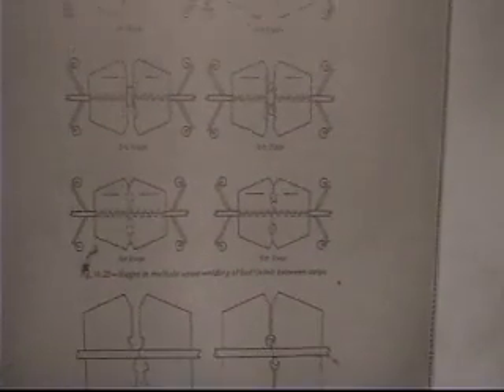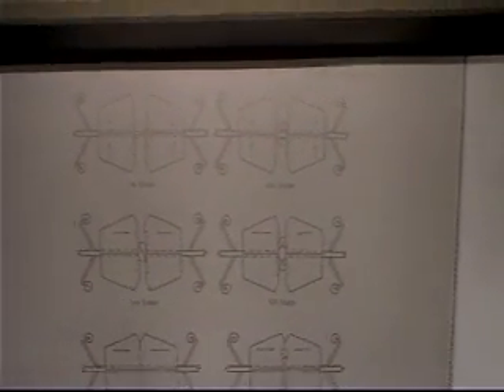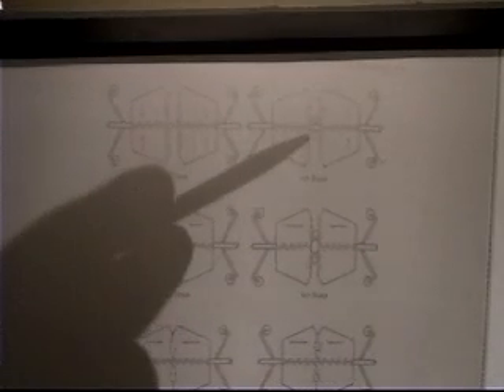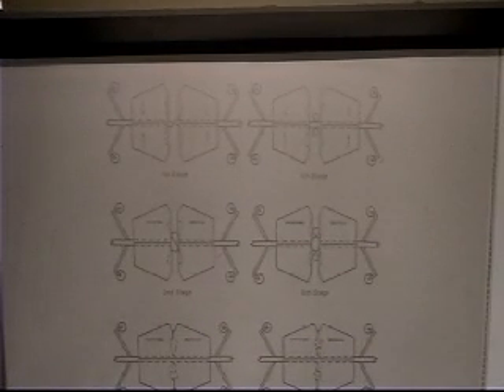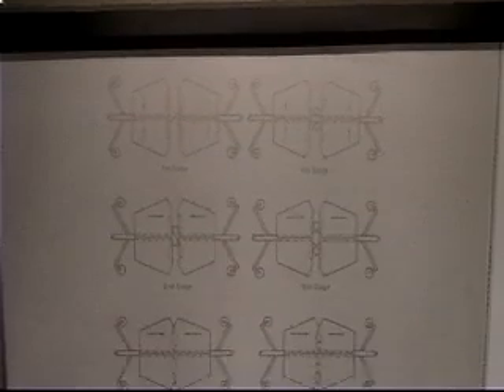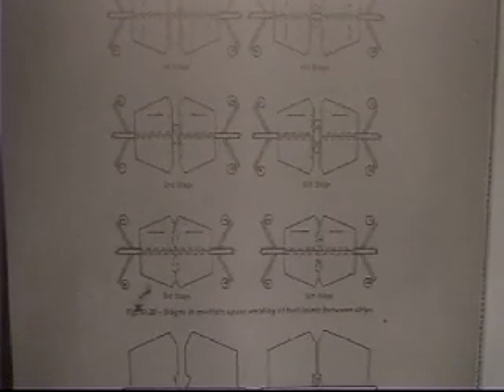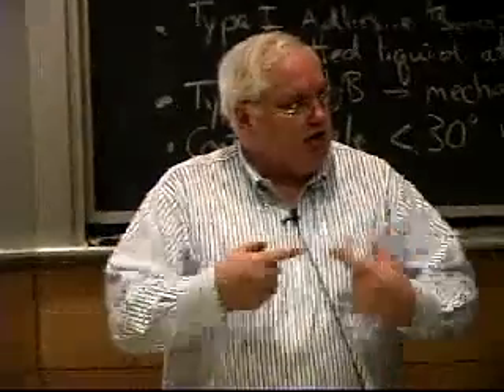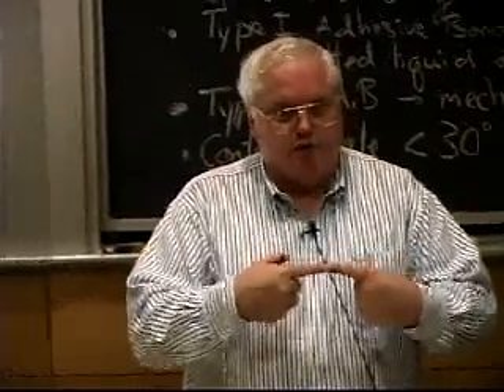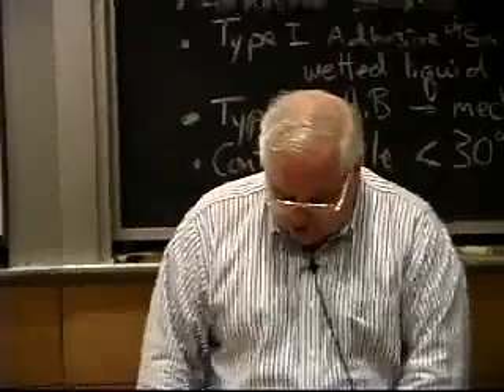Well, it turns out people actually weld aluminum wire together in the aluminum wire drawing business. This comes out of the welding handbook. I think you've got a copy of this, but it doesn't really matter. You can't just push two wires together to bond them because you don't have any interfacial sliding. So what they do is they have some dies that hold the wire, and they kink it sideways and squeeze it once, and now you're getting interfacial sliding because the two are at a funny angle. You then do it several times, so you get more and more interfacial sliding, and you can essentially make near perfect welds in aluminum wires by cold welding. We can't do that with iron or copper because we can't get enough deformation in wires with small ends like that. But with aluminum or indium, you could do it. So these things actually do work in certain cases.